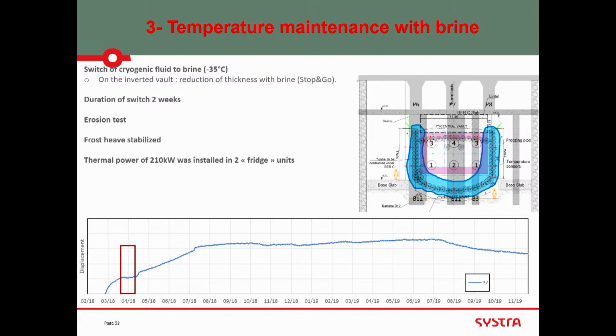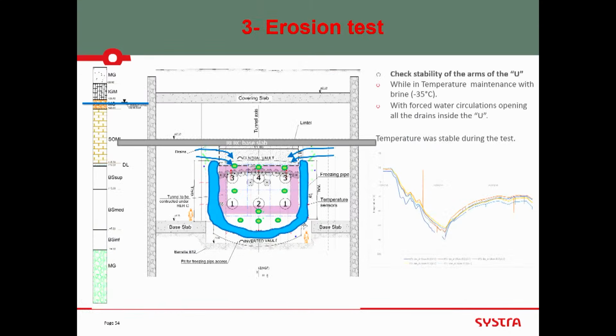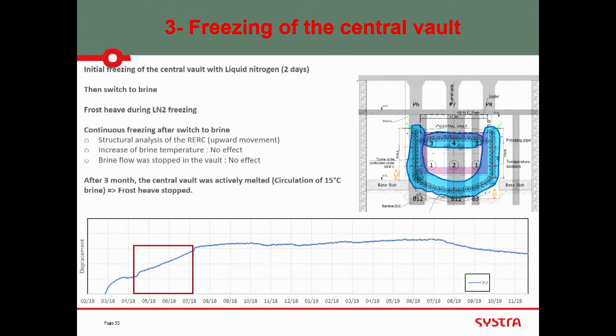and do a test. As I said, we did not have success in grouting this area because of low pressure, and we were very afraid of erosion because the water was going downward into the excavation. So we were afraid that the frozen area was decreasing with time, and then suddenly we would get flow. So we did an erosion test. This erosion test was done by draining inside the box, so putting the flow of water from outside to inside the box, going next to where it was frozen. And it was stabilized, so we didn't have to put in more energy. Then we froze this area. So we had kind of upward movement always at pile 7, so column 7.